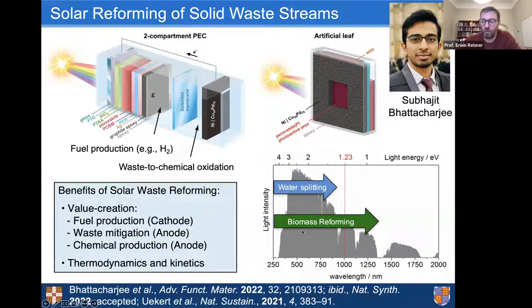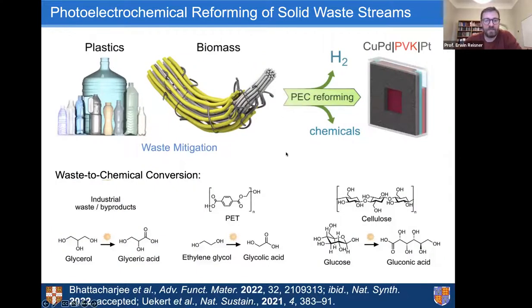And the advantage of thermodynamics is just illustrated here. If you think about a single light absorber and you want to drive water splitting, since it's such a thermodynamically difficult reaction, you can really only use the UV and possibly a bit of the blue light. On the other hand, for waste reforming, since it's thermoneutral, in principle you can use the whole visible spectrum. And that's exactly what we're doing here in this artificial leaf, where we use the perovskite that really absorbs the visible and the UV. And this is just some of the chemistry we have been showing already.